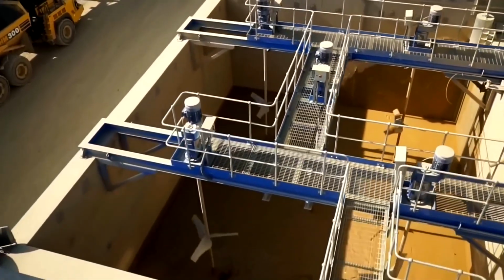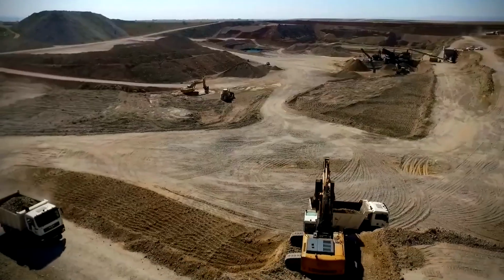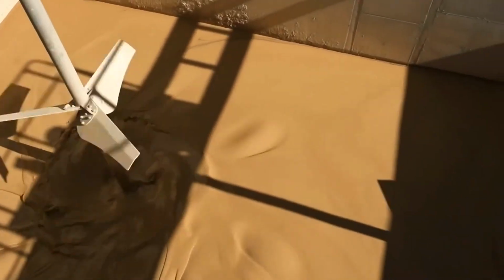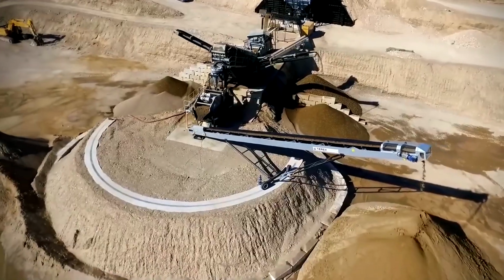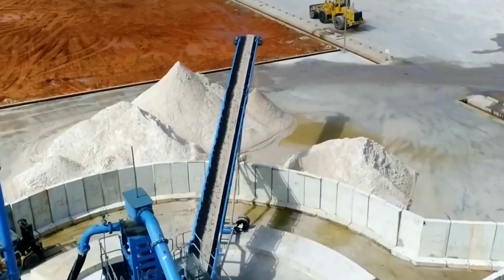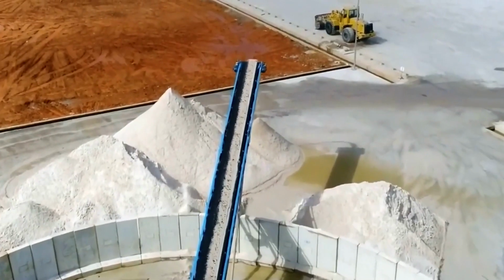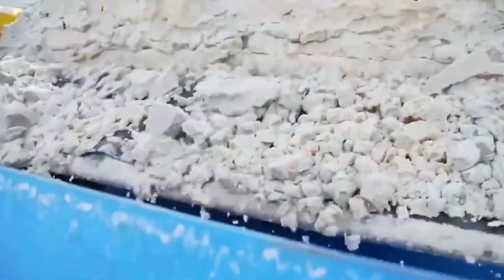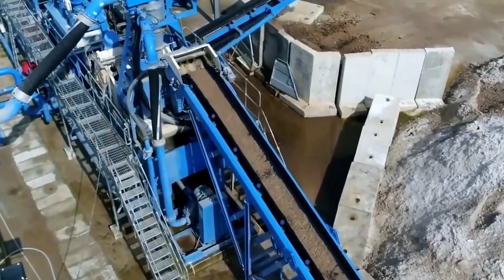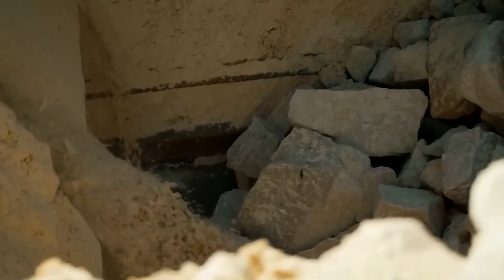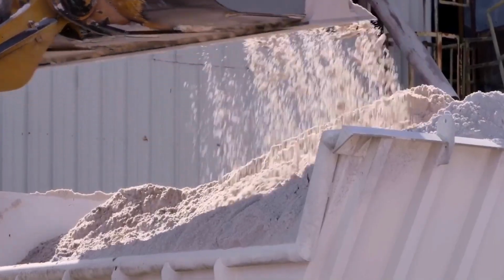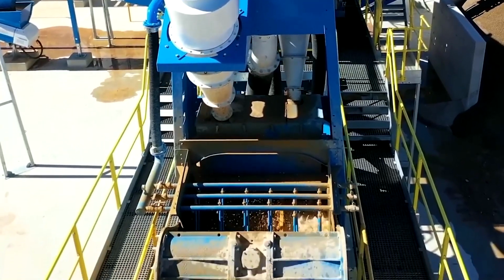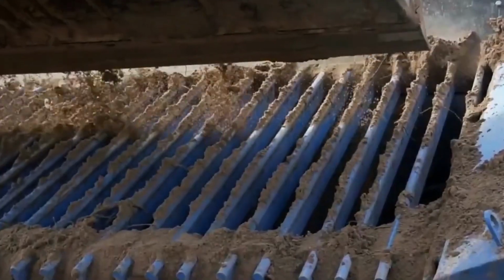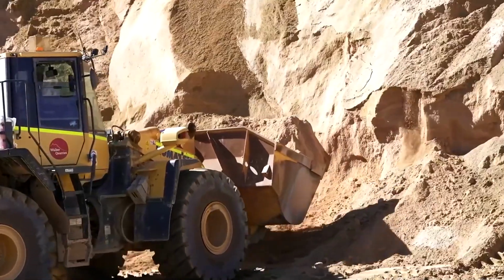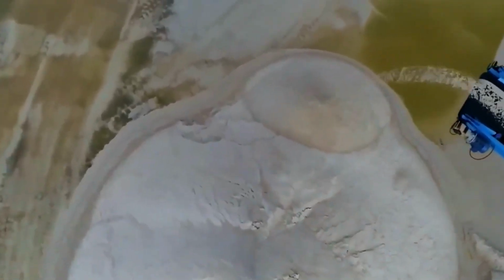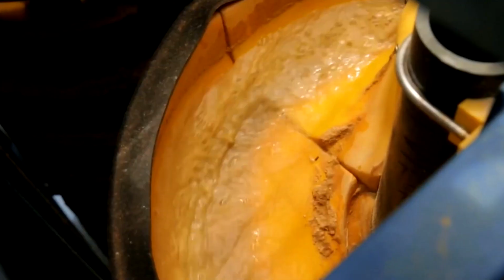Only the grains that meet the precise size specifications are permitted to pass through to the next stage of refinement. From there, the sand enters powerful agitation chambers, where it is scoured by high-pressure, needle-like jets of water. For nearly 15 minutes, the mixture is churned relentlessly, cleansing every grain before it begins a controlled descent into a spiral separation system. Inside the spinning vortex, centrifugal force takes over, casting heavier metallic impurities outward to be filtered away. The lighter, more refined stream continues onward, passing through a final mechanical separator that captures any lingering traces of iron before being dried and sealed in 1-ton bags, ready for the factory.